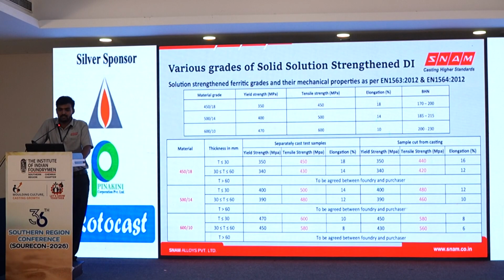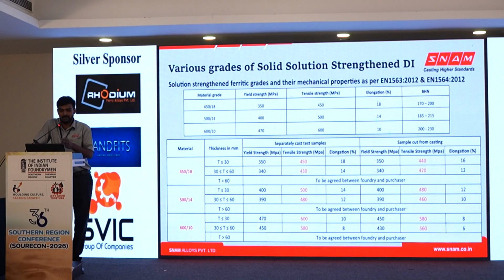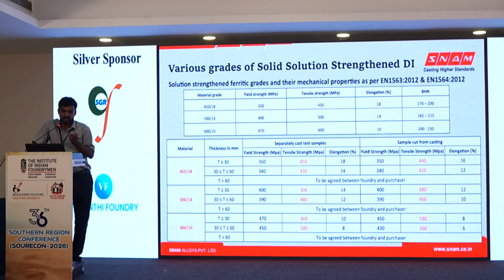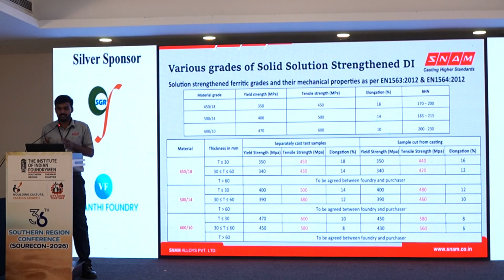So now, various grades of solid solution strengthened ductile iron. As per EN standard, EN 1563 and EN 1564 issued in 2012, we have three different grades of SSFDI, which are 450/18, 500/14 and 600/10. When we compare SSFDI with the conventional grades, we have an increase in yield strength and elongation, and we can also achieve the Brinell hardness number with minimal variation.